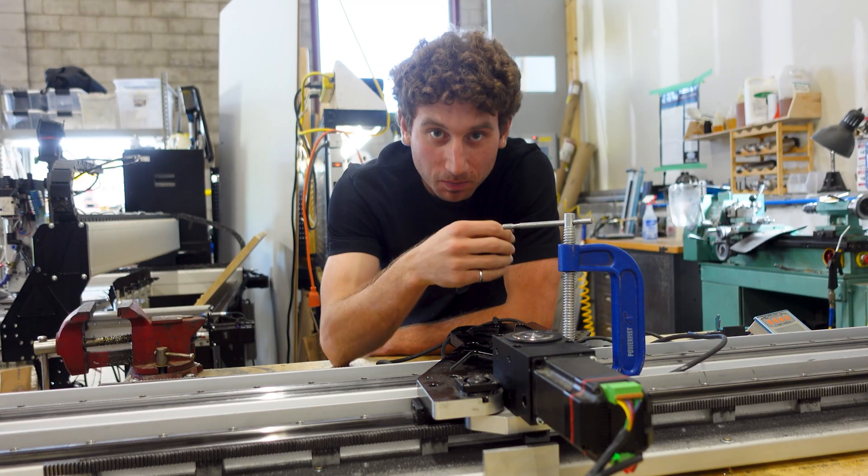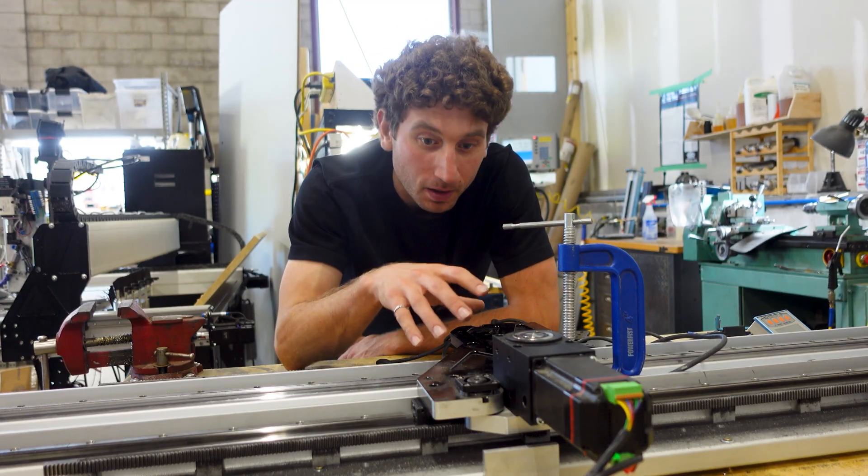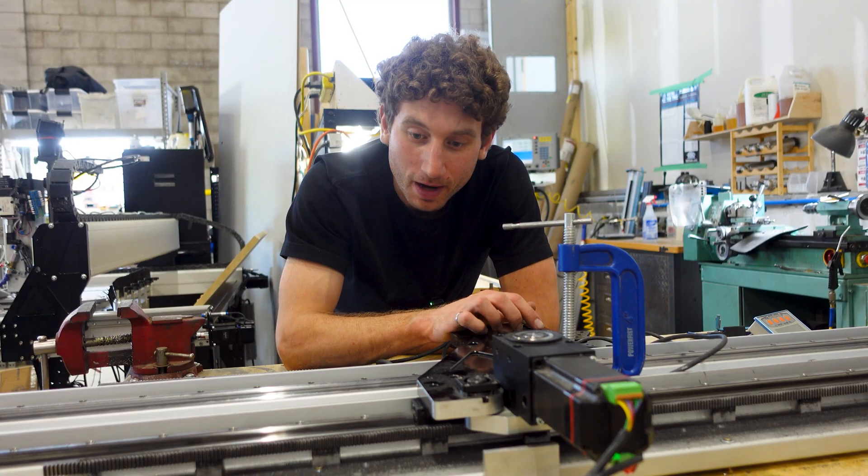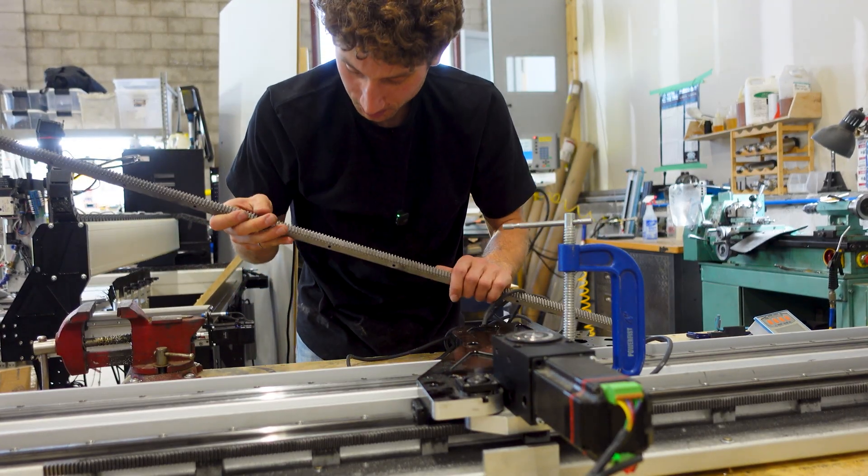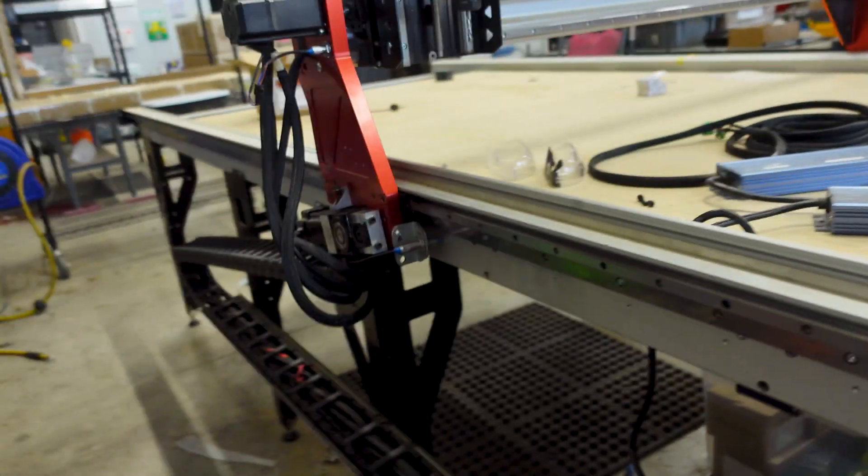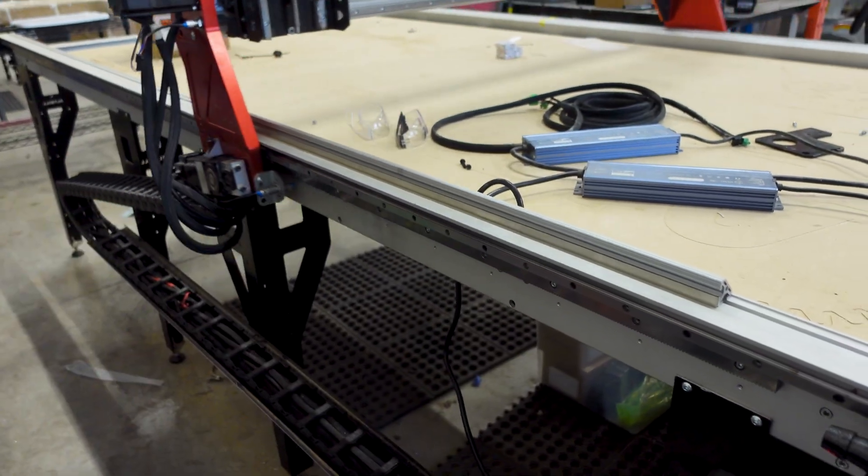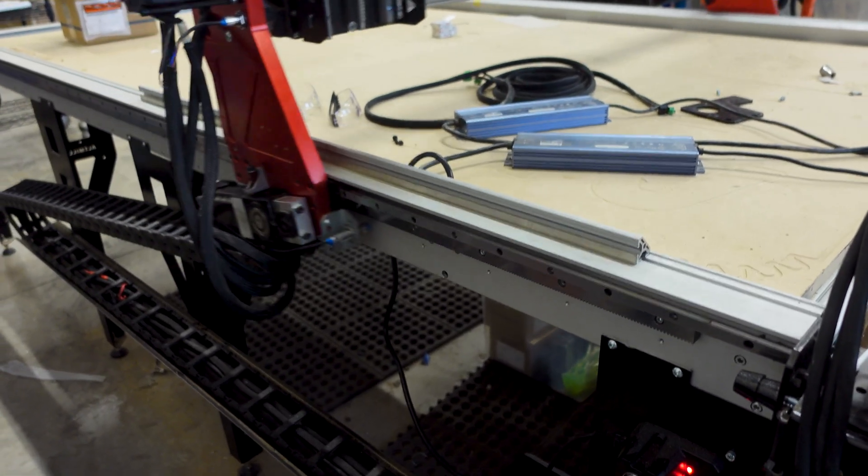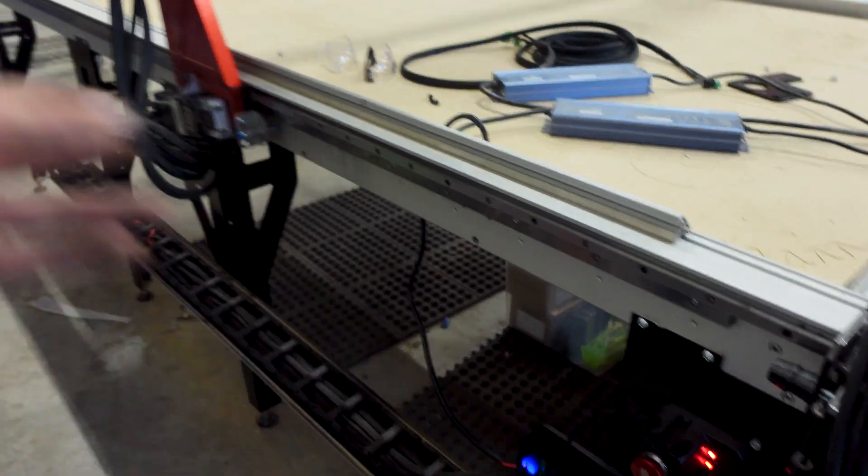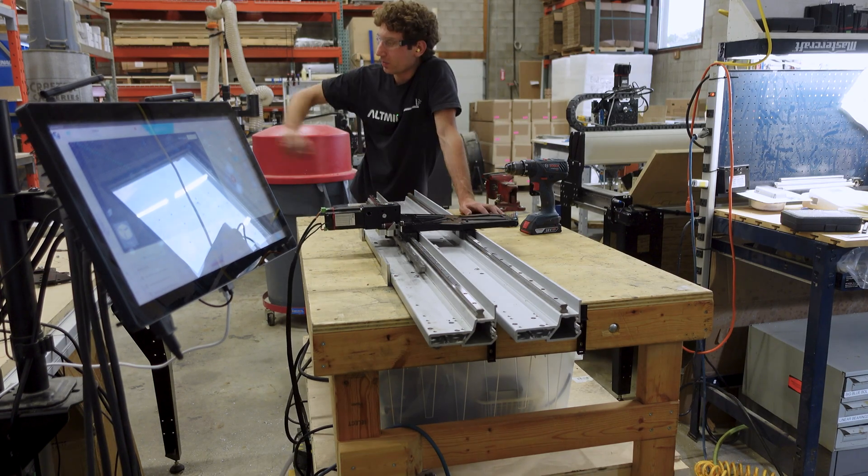Obviously it wore right down which is completely expected and a good thing really because what it is is it's a building block. I now have a baseline of a failed rack and pinion setup which is just two non-hardened 1045 material racks and pinions purchased from stock, the internet. Got these new nitrided racks in from a local place that nitrides things. This is a nitrided rack. In there is a nitrided pinion. Other side, this side is regular stock 20 Rockwell hardness and nitrided pinion. So the bet is that pinion stays good, wears rack down because it's so much harder or at least sees far less wear and the rack is the one to suffer more than the pinion. Whereas right now, normally we see the pinion suffer far more than the rack because the pinion is just doing so many more reps. That pinion is turning and turning for one length. Whereas, you know, one length the rack sees per tooth, it sees one hit. It's going to run over the weekend until it fails.